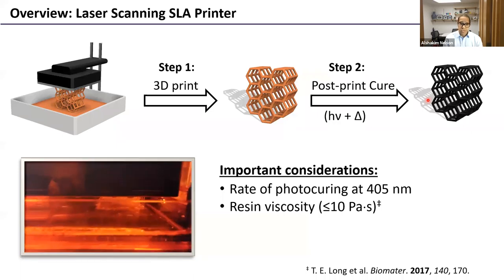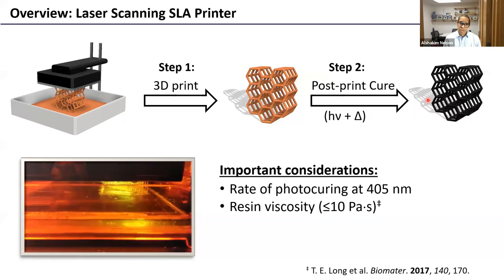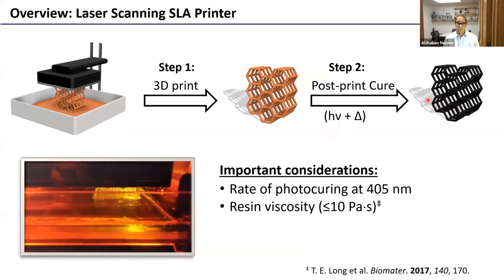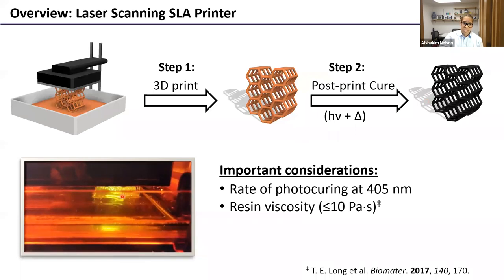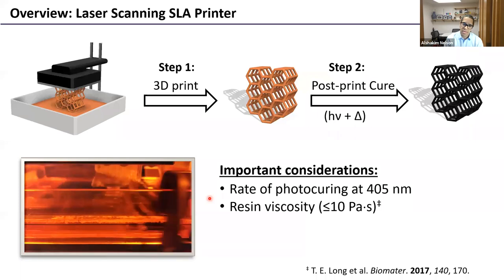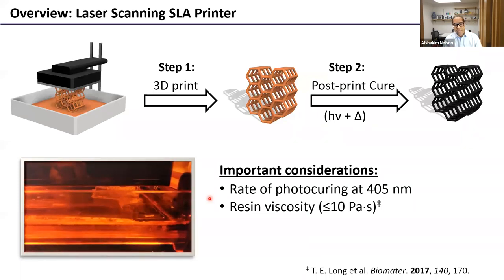So there are two important considerations here when using this type of printing. So we're using a commercially available Form 2 printer, and this uses this rastering laser. So you can see how fast this laser is rastering across the surface. And what it is doing is it's drawing the pattern of just that one layer. And that layer is anywhere between 50 microns and 100 microns thick. Okay, and so now you see this liquid resin being swiped, and this liquid resin has to reflow because since we're printing one layer at a time, we have to apply that next layer of resin for printing. Okay, so the two most important considerations then: the rate of photo curing, or how fast we can cure the material to harden it, and then the second is the resin viscosity. So it's really important that this resin be liquid or have a low viscosity.